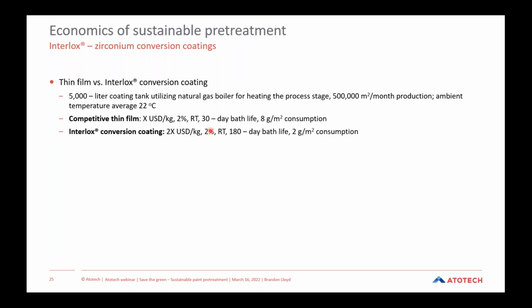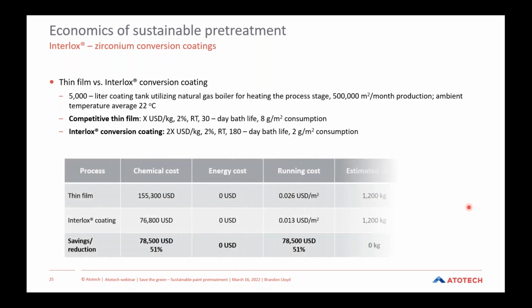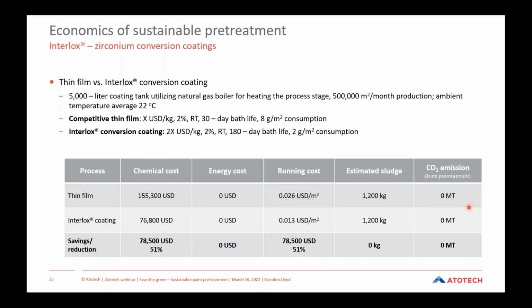Similar operating concentrations and operating temperatures at 2% in ambient temperature. But here we're able to increase the bath life quite a bit, as well as reducing the chemical consumption. So what does that equate to for an applicator considering a change? The chemical cost can be greatly reduced in this scenario by about 50%, and most of this is associated with the reduced chemical consumption.